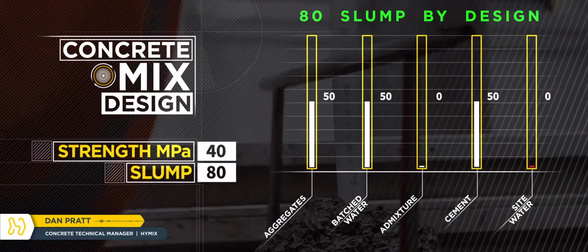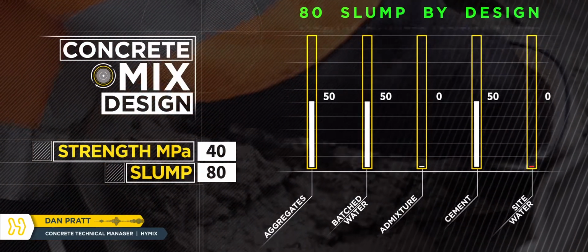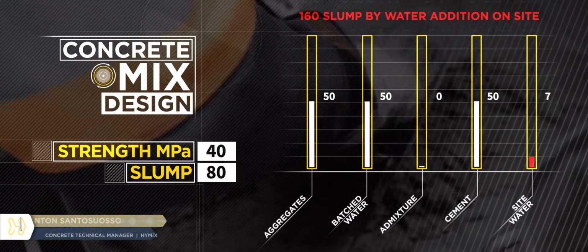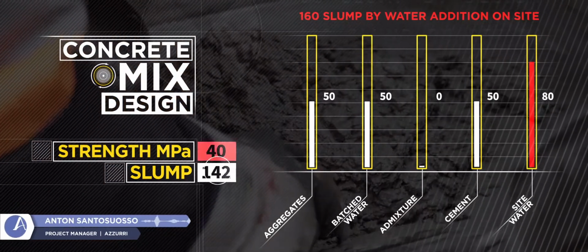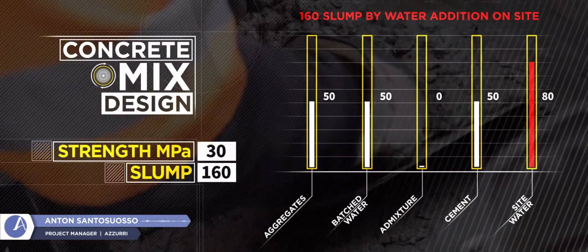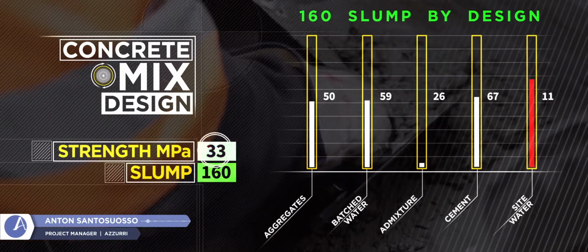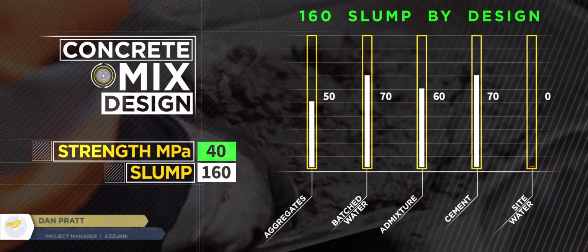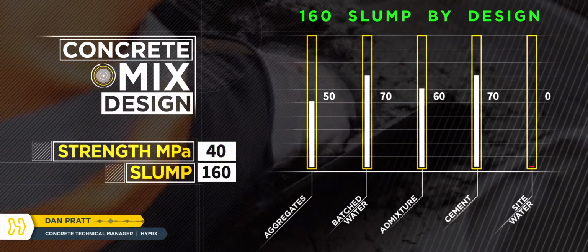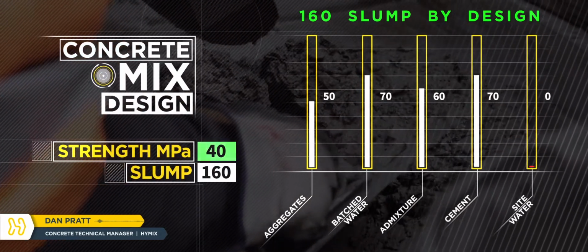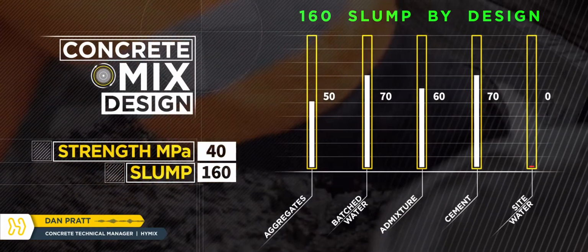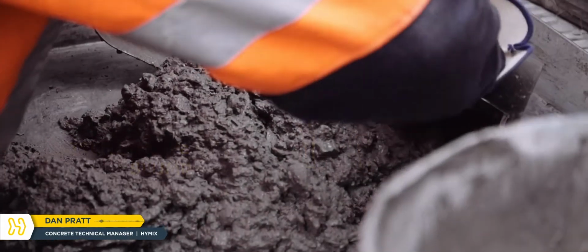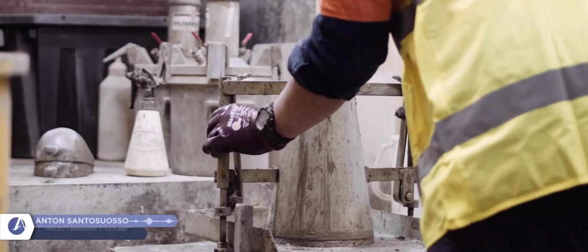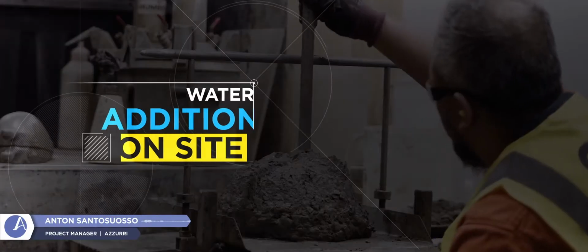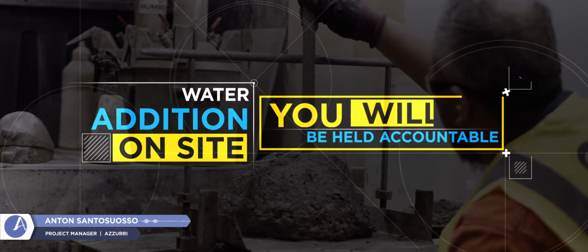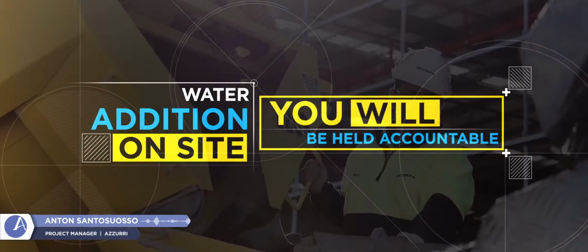Generally, if we design it at 80 slump and it tests at that, we should achieve our maximum strength. You can't take a concrete that's designed at a slump of 80, 90 or 100 and increase it to 180, 190, 200 slump to assist with pumpability. Now, if they want it at 160, we can still maintain that water-cement ratio by design. So we don't lose strength, we don't increase shrinkage, we don't encounter any of the problems from diluting the product. And if there are issues further on down the track, they're going to go through their records and determine who, when and why actually added the water.